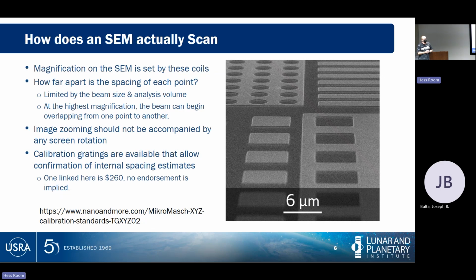And if we're missing something important, it will not total to 100%. It will not have enough counts to account for everything that would be there, because that would mean something was doing an X-ray fluorescence and we hadn't detected it. So we need to go back in and check again for some other element that we might have missed. And even then, microprobes can often not be perfect if you're analyzing a lot of heavy stuff. So sometimes you do the best you can. And the next step beyond that would be laser ablation ICP-MS, which is quite good at measuring various low abundance elements if you can ablate a 25 micrometer area of something.